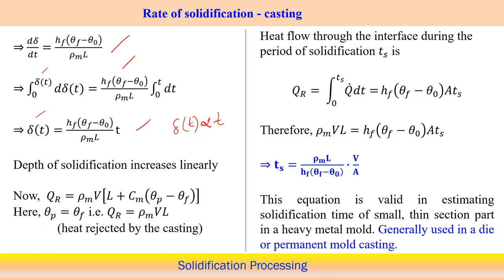Now, from another perspective, we can calculate the total amount of heat release, Q R, which is rho m v into L. Here rho m into v is the cast volume, and there is a term C m (theta p minus theta f), where theta p is the peak temperature, that means the superheated temperature, theta f is the freezing temperature, and C m is the specific heat of the cast metal. If theta p equals theta f, we are basically neglecting the superheated part. Therefore, Q R can be calculated as rho m v into L. That is the total amount of heat rejected by the casting.